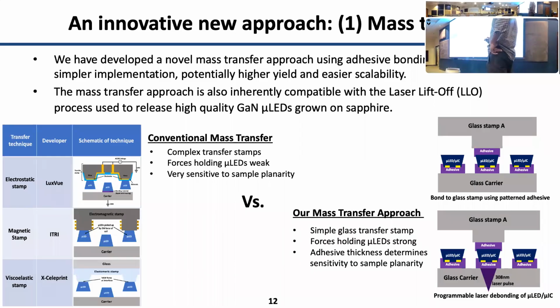So if you see the figures in the bottom, the left side summarizes the conventional mass transfer approaches. If you can see the table, it either uses an electromagnetic technique, by using either an electrostatic or a magnetic stamp to induce electromagnetic forces to pick up the devices from a carrier, or it uses a viscoelastic stamping technique wherein a PDMS stamp is used and the devices are picked up using van der Waals stiction.